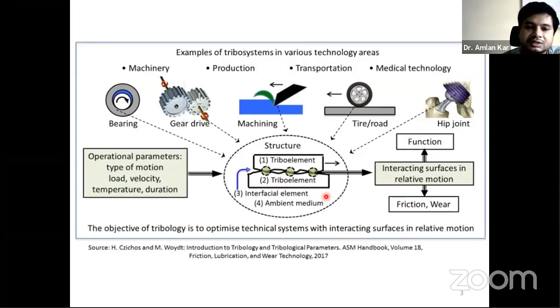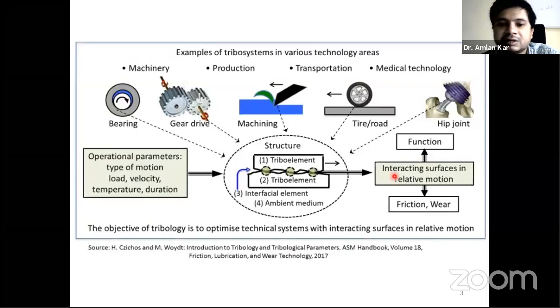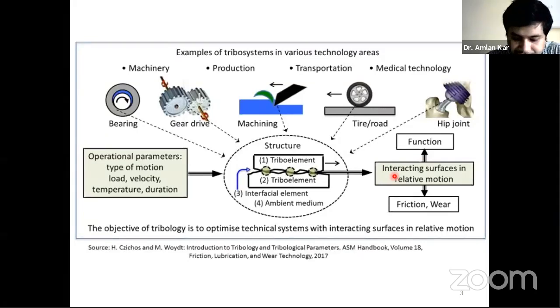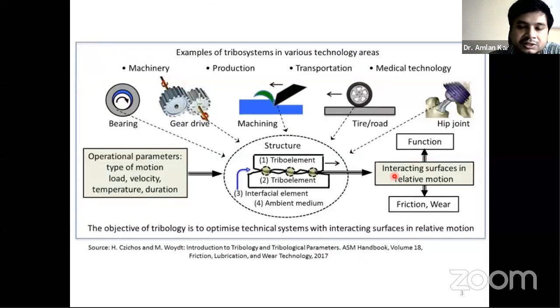And the only thing is that during the relative motion, there is a deformation at the interface, and that leads to an increase in the temperature and welding, micro welding, taking place. And all of it finally affects the friction and wear behavior at the interface. The deformation behavior I am talking about, at the surface and subsurface level, depends on different process parameters, like the load, the velocity, temperature, and the duration of load application.